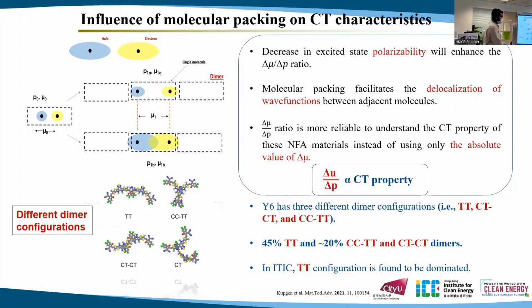There is already some literature showing that Y6 has different dimer configurations: core-to-core interactions, core-to-terminal interactions, and terminal-to-terminal interactions. In Y6, 45% of the formed dimers are terminal-to-terminal, and the rest, around 20%, are CC-TT and CT-CT dimers. For different dimers, the electronic coupling and the delocalization will be different.